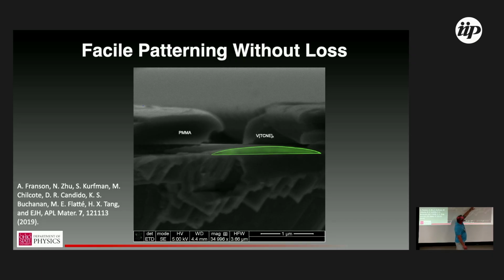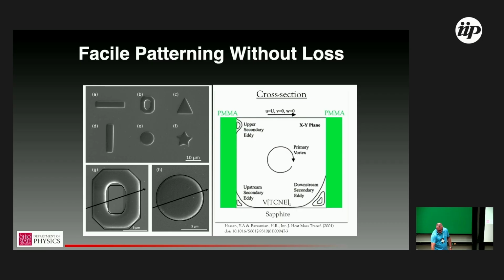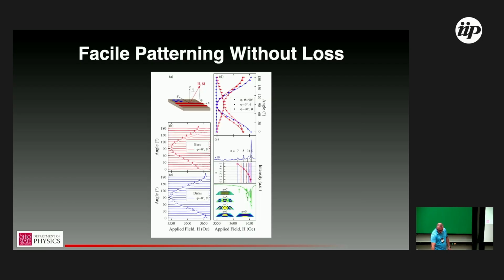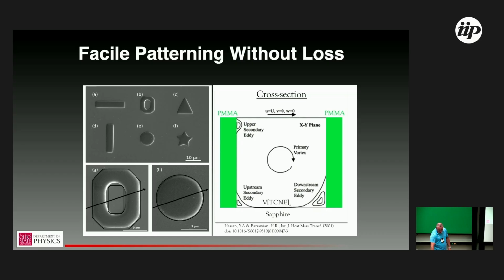And so you can see this structure is about at the fidelity limit, where the thickness in the middle is sort of the bare thin film thickness, where we really have fresh precursor coming in at the base rate, and then the edges are tapering off. So if we make this wider, those tapered regions are basically fixed width. And if you make it very small, then you eventually suppress deposition in the middle. So that's important to understand in terms of the shape.